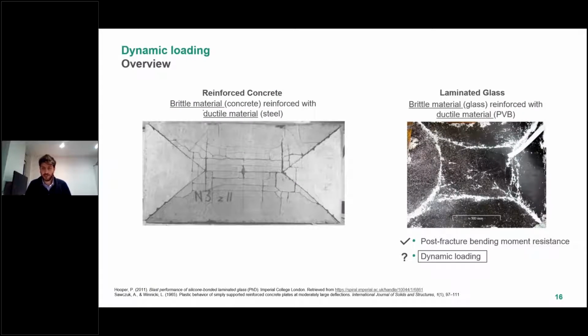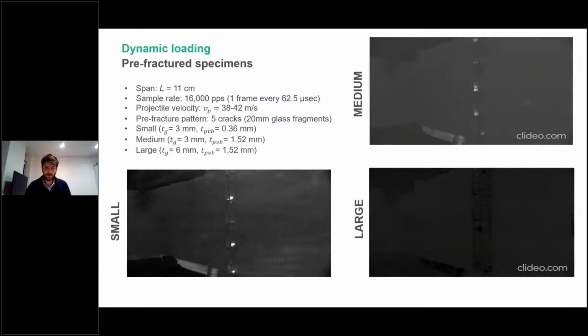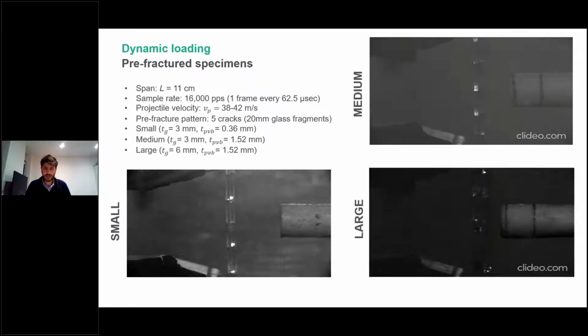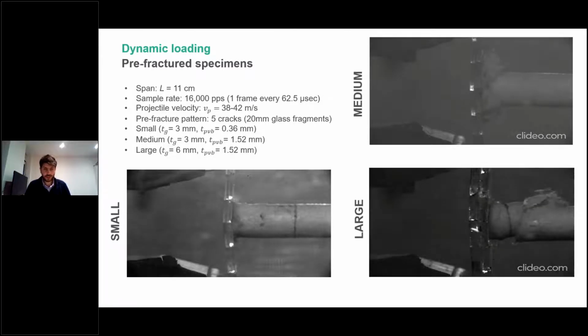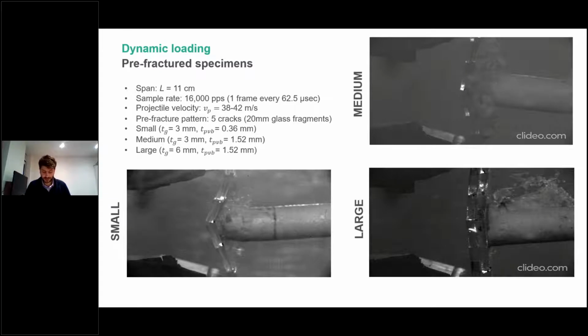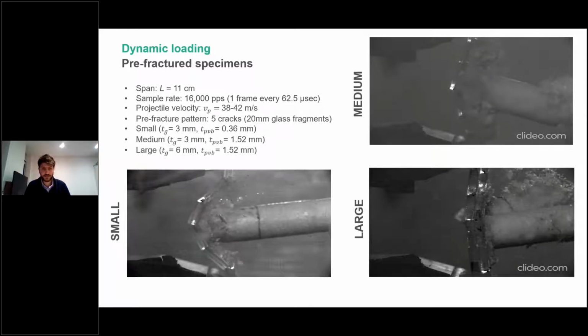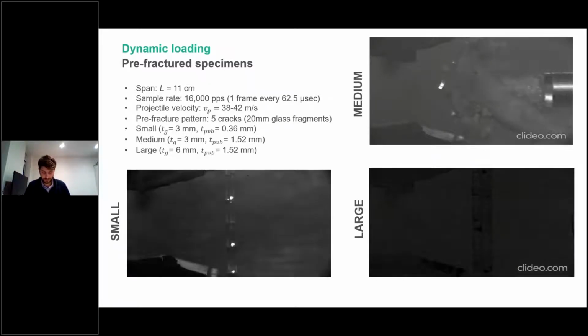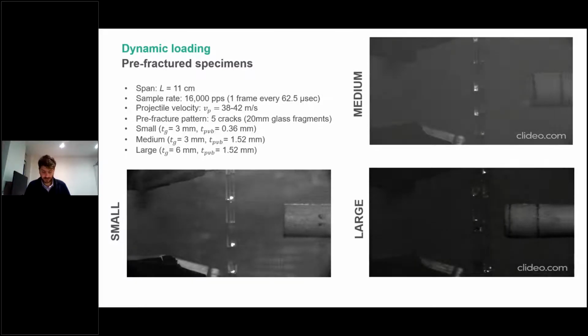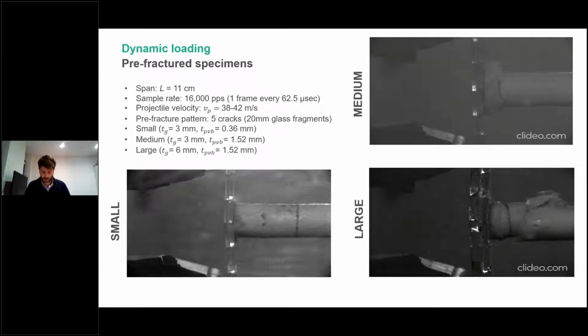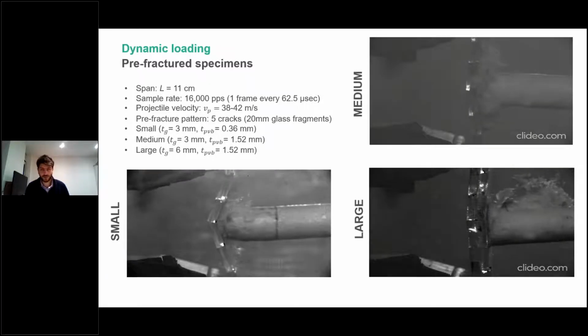Now moving on to dynamic loading, to investigate the effects of inertia, I performed impact tests by launching foam projectiles from a gas gun and recording the response with a high-speed camera. The pressure time history resulting from this impact simulates the positive phase of blast loading. The same specimens, pre-fracture patterns, and span as the low temperature bending tests were considered in the impact tests to directly assess the influence of inertia.